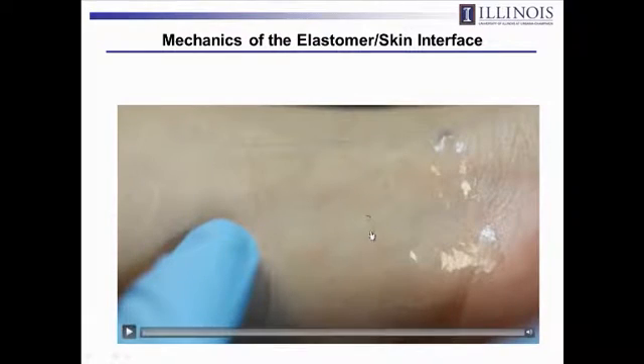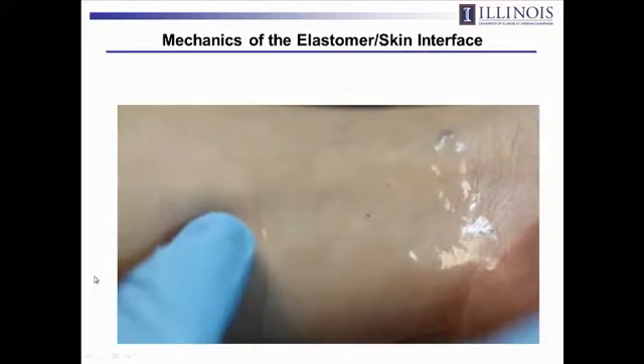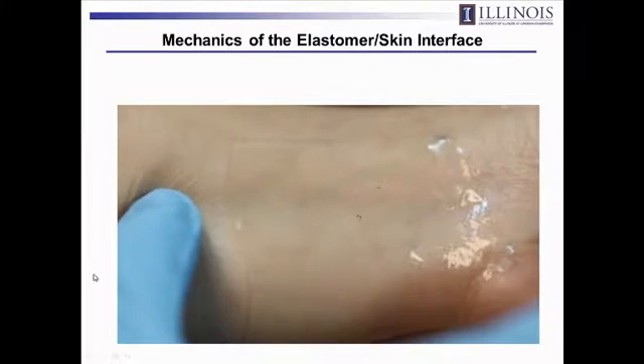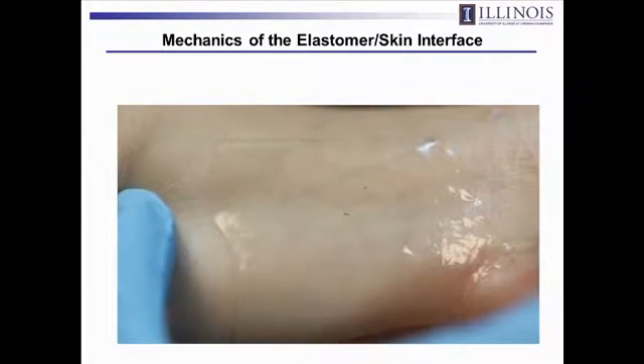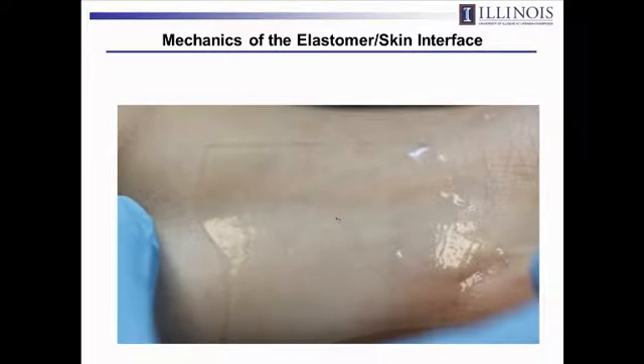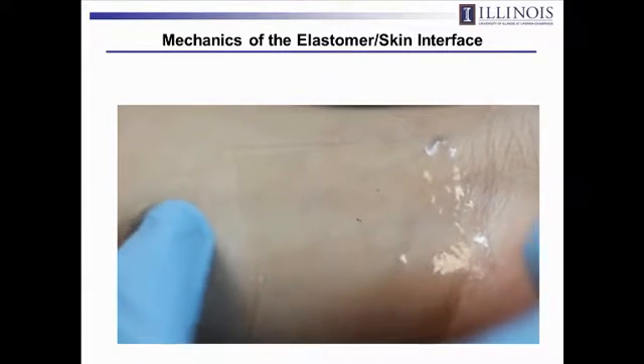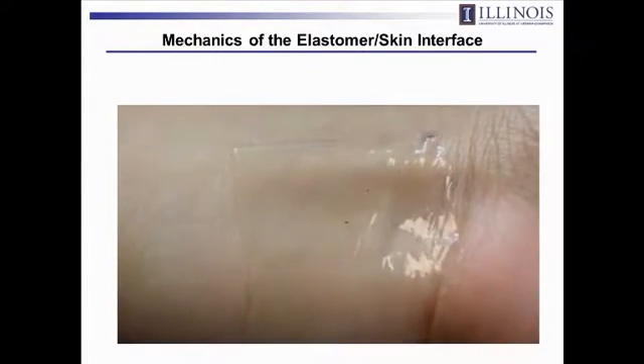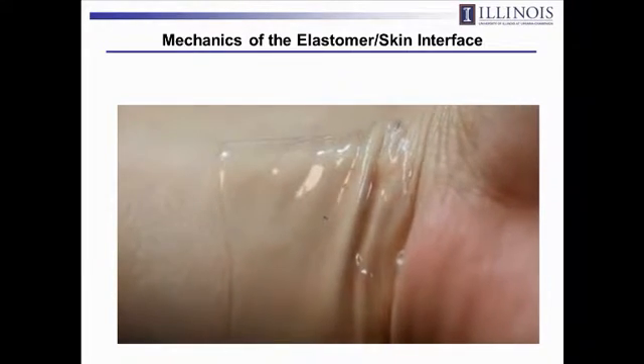Now with lower modulus, here's what happens. Same thing, same region of the skin, same interface chemistry, same adhesive strength. It doesn't delaminate, and that's just because you've minimized the interface stresses. And it sticks now, it just clings, and you can move your wrist around and it stays put.